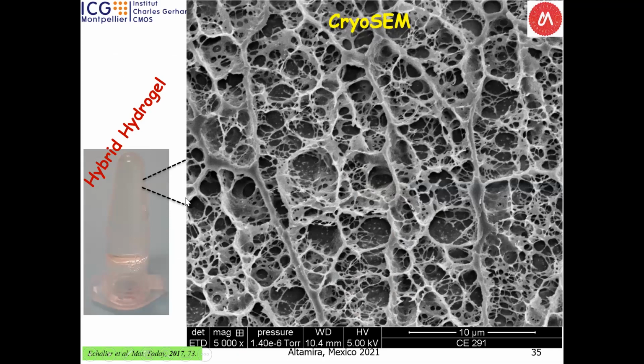Just to show you some cryo-SEM images, just to see that we have a huge porosity. It's important for the delivery, for the connection, to introduce cells at the end. You know, you need some volume, some space to make cell development inside your hydrogel, not only on the top of your hydrogel. So it's very important to control the porosity.